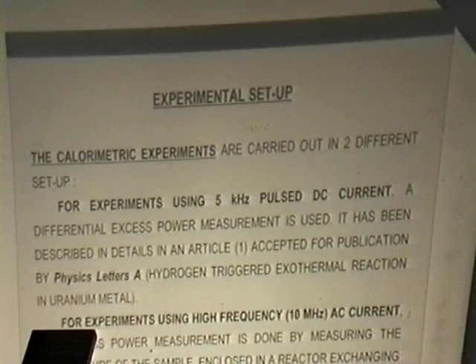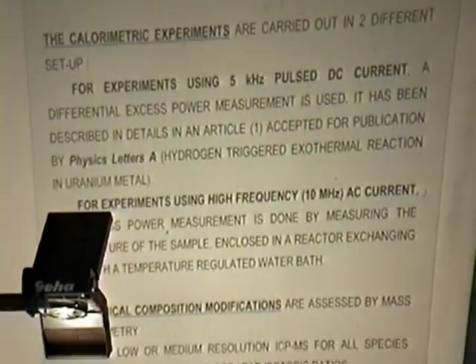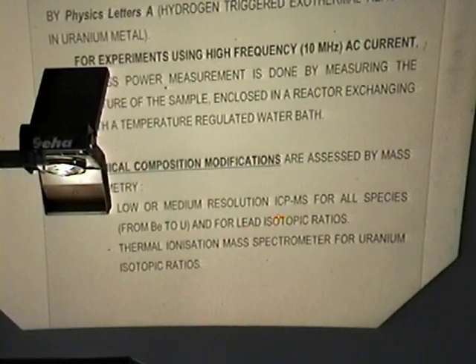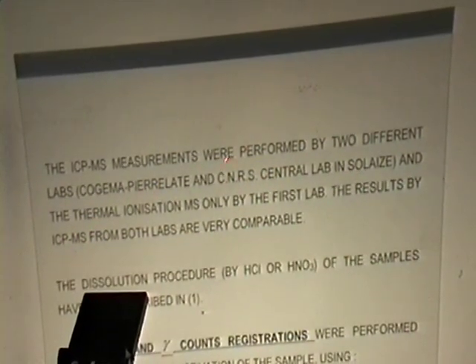The chemical composition was assessed by dissolving the total sample, and we are using a low or medium resolution ICP-MS for all species from beryllium to uranium, and for lead isotopic ratios, and a thermal ionization mass spectrometer for the uranium isotopic composition. These measurements were performed by two different laboratories. One is the central laboratories of the CNRS, the Centre National de la Recherche Scientifique in Solaize, and that's for all the elements except uranium, and for the uranium, the measurements were performed by Cogema Laboratories in Pierre-Latte in France.